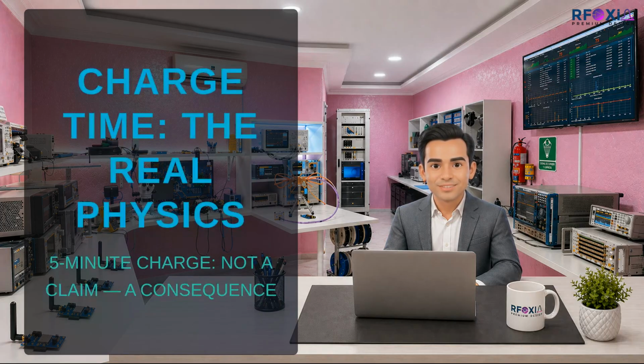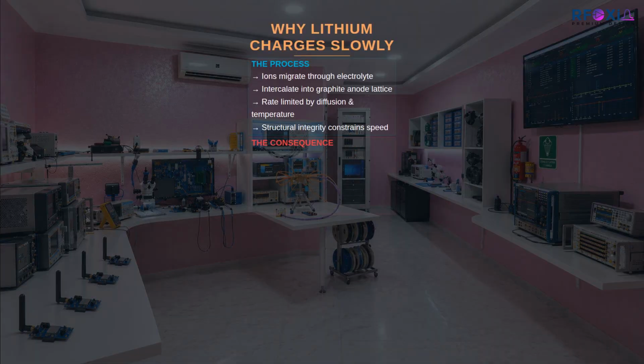A lithium-ion cell charges slowly for several compounding reasons. First, the storage mechanism is electrochemical. Lithium ions must physically migrate through an electrolyte, intercalate into a graphite anode structure, and settle into lattice positions. This is not an instantaneous process. The ions move at a rate limited by diffusion coefficients, temperature, and the structural integrity of the electrode material itself. Push ions in faster than the lattice can accept them, and you get lithium plating, metallic lithium deposited on the anode surface rather than intercalated into it. Lithium plating is a safety problem. It creates dendrites. Dendrites grow across the separator. You know how that story ends.